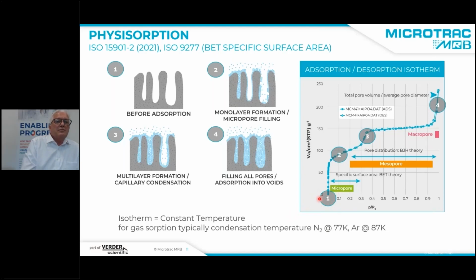In the beginning, we start with vacuum. We evacuate the system at number 1. You see here the clean surface of our porous material. Then we start to introduce step by step our gas molecules, and these will fill micropores or lay around the surface. We are here in region 2, where we have monolayer formation, from where we can calculate surface areas or micropore filling. Later on, in the mesopores, we have capillary condensation, so filling of pores with a liquid below saturation pressure. And at the end, we have filled all our pores and voids, and we can determine the maximum pore volume, for example. So we get at least 3 main pieces of information. One is the specific surface area from this region, and pore size.